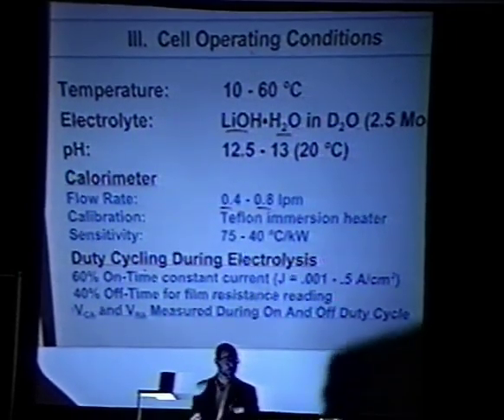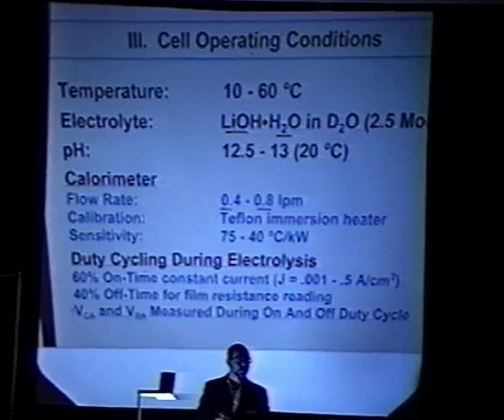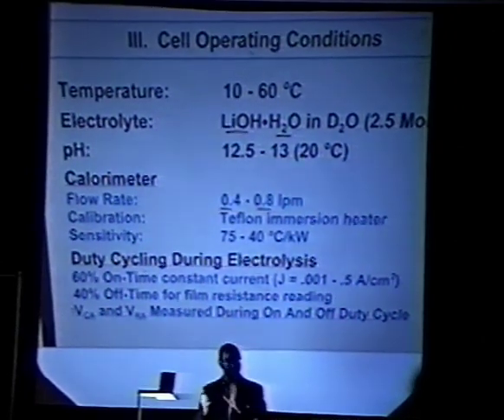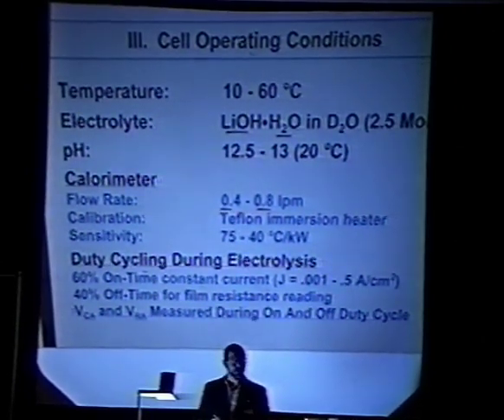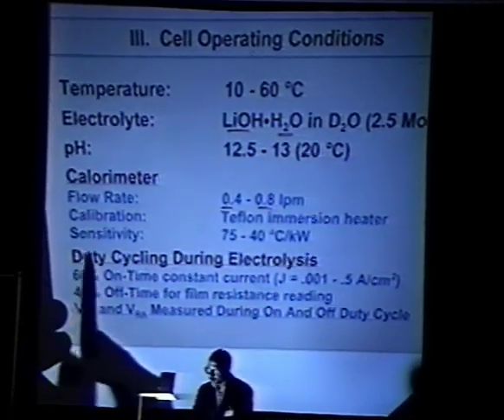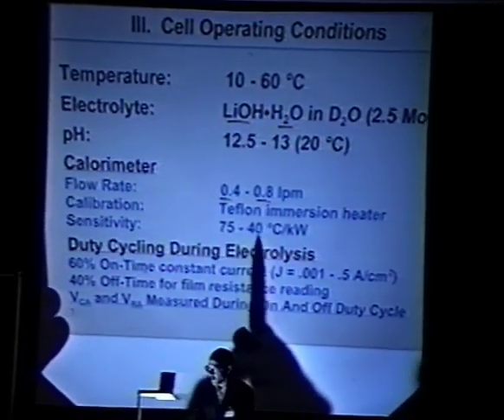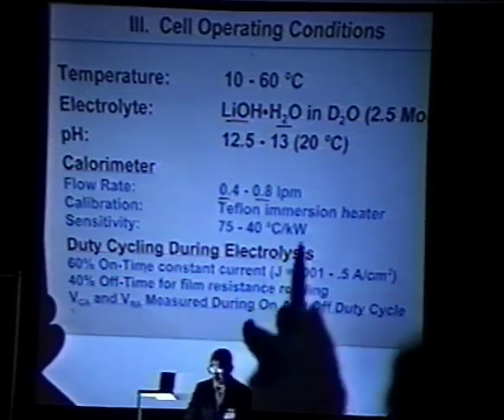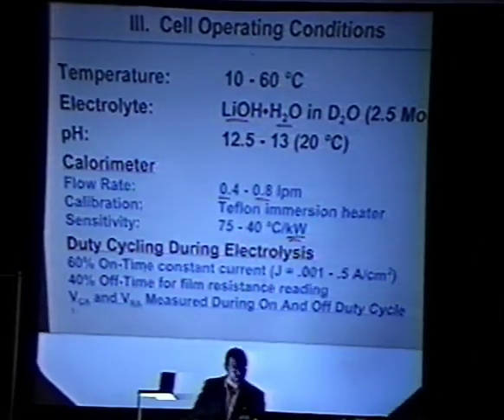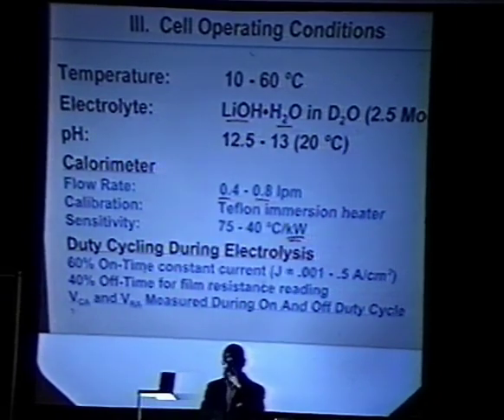I found this calorimetry is about 90% efficient. If I put in, say, 500 watts, I can actually detect the 450 of that. The sensitivity for the data today is about 75 to 40 degrees centigrade per kilowatt. And these are large numbers in terms of the power.